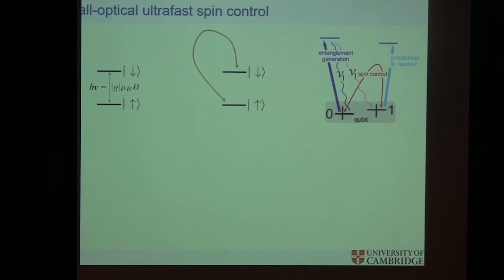So we need to control the spin. For that purpose, we have yet another expert in the audience that has done spin control. Again, anything I'll talk about, there will be one other person who has done that in the past. Normally, you can do magnetic coupling for the spin state, but we use optics. We use the excited state to do stimulated Raman type transitions, which makes things very fast for us. So instead of direct coupling, which is typically on the order of 10 nanoseconds or so to be able to do a full swap, we're able to do it in 3 picoseconds. So that gives us an extremely fast time scale for doing spin rotations.